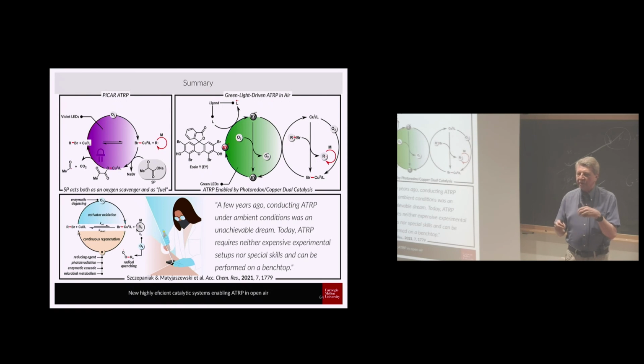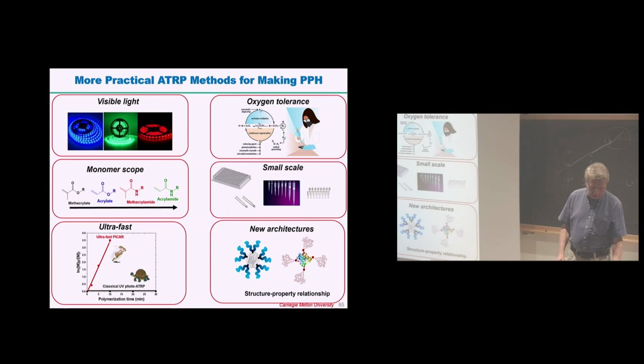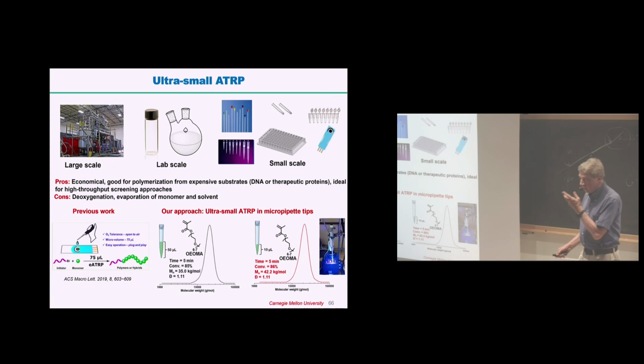So it's a little bit of a reducing agent, a little bit of control in water especially, of halide concentration and some others, but this opens possibility of manipulating macromolecular architecture. And we can go sometimes to systems based on visible light, on this oxygen tolerance, working on a very small scale, making new architectures, going to faster reactions. And here's an example of going from thousands of liters to the microliters. So this is done with a printed electrode that you can make DNA polymer bioconjugates, 75 microliters.